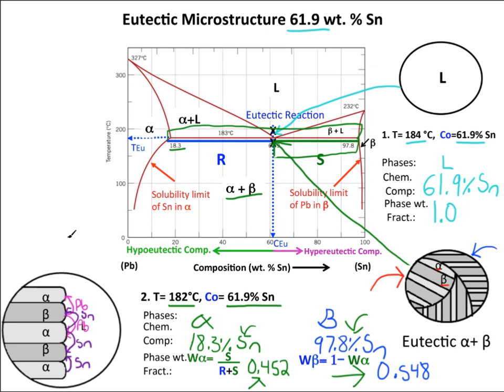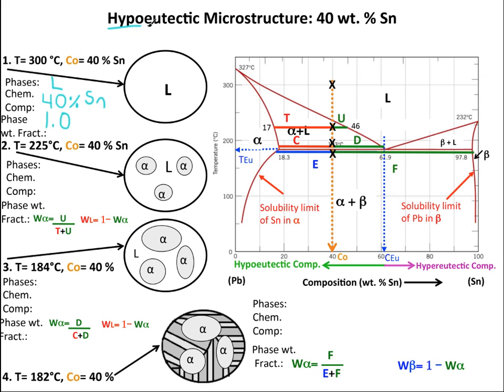Where do these plates come from? When the liquid goes to solid, the geometry of adjacent platelets provides a short path for atoms to solidify as plates of alpha. Alpha rejects tin, and adjacent plates of beta reject lead. The microstructure consists of alternating growing platelets of alpha and beta whose fronts eventually run into each other. It's also important to note that the phase weight fraction is approximately equal to the amount of area that the phase takes up in the diagram.